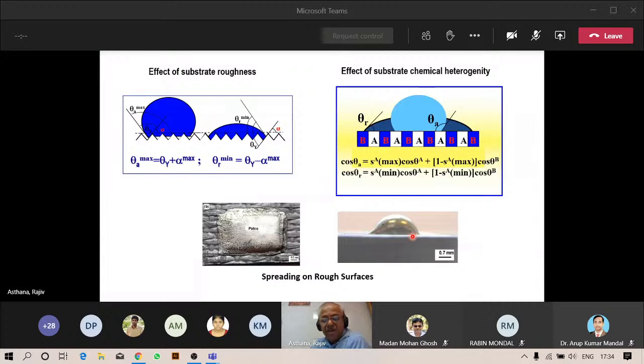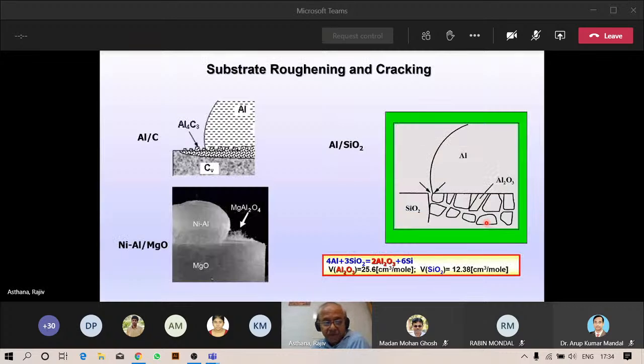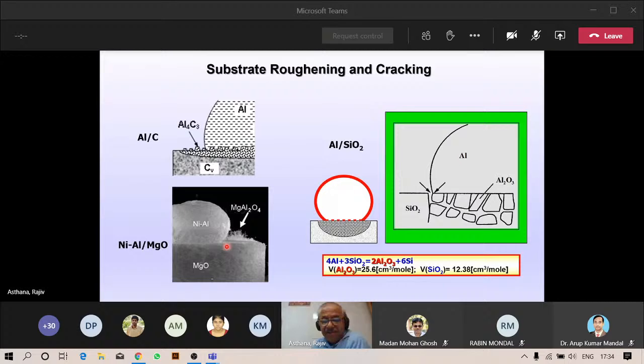There are a lot of things happening during the spreading of liquid on solid in reactive systems. So in the case of aluminum spreading on carbon, you're actually forming aluminum carbide by a strong exothermic reaction, and the aluminum carbide crystals form ahead of the interaction zone or the liquid spreading liquid. In the case of nickel aluminum on magnesium oxide substrate, we see whiskers of a magnesium aluminate or a spinel whiskers. So the surface is roughened. In aluminum silica, a very common system, there is reaction taking place, you form aluminum oxide, and there is volumetric change that can cause cracking in the substrate.